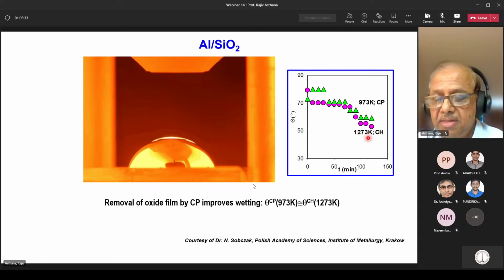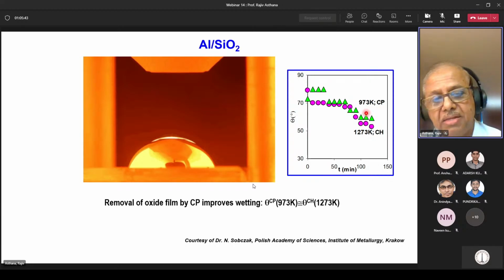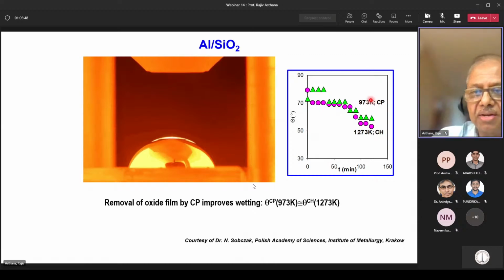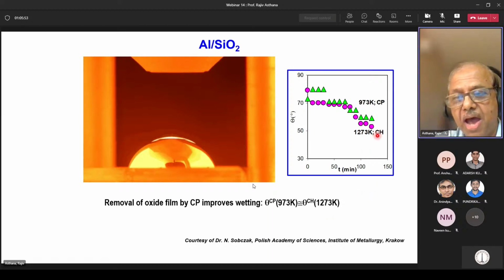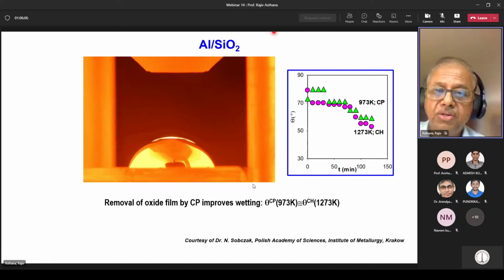contact heating gives you the same contact angle values at 1273 Kelvin that you obtain by this method, even at 973 Kelvin. So even at low temperatures, you are able to get the correct contact angle that would be possible in contact heating only at very high temperatures where the oxide will dissociate by itself, either by dissolution in the liquid or gaseous suboxide Al2O formation and other things. So this is the case of aluminum on silica.